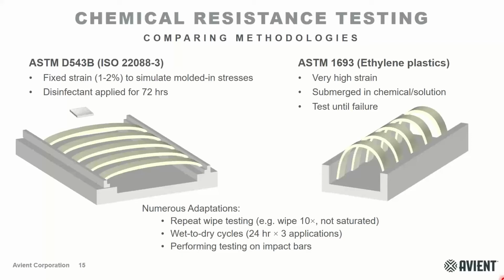And the reason for that is because they have a very high strain in this test. The bars are being bent almost 180 degrees. They're submerged in a chemical solution and they're tested for upwards of 60 days or so until the material fails. And then they use that time point as the metric for how resistant it is.